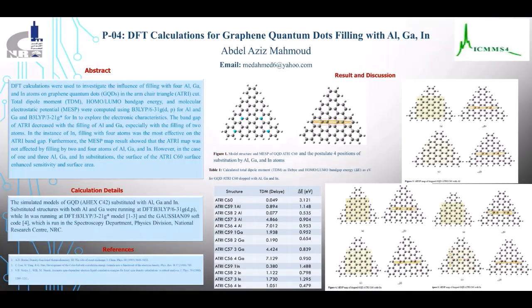Poster number 4 presented by Professor Abdul Aziz Mahmood titled Density Functional Theory Calculations for Graphene Quantum Dots Filled with Aluminum, Gallium, and Indium. Density functional theory calculations were used to investigate the influence of filling with 4 aluminum, gallium, and indium atoms on graphene quantum dots in the armchair triangle cut. Some descriptors were calculated for model molecules to study the effect of substitution. Such descriptors, including the total dipole moment, the highest occupied molecular orbital and the lowest unoccupied molecular orbital bandgap energy, and the molecular electrostatic potential, were computed.